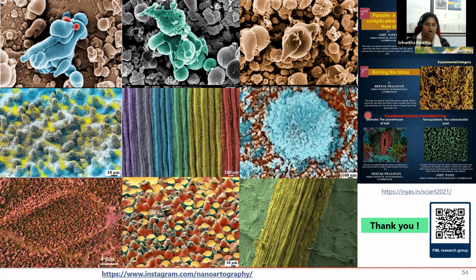So as you have seen, in all the samples, the surface roughness is reducing as we have increased the density, isn't it? Yes, madam. But remember, we are never testing a dry specimen. We are always coating or infusing the high viscosity liquid in it. And that oil is flooding your surface roughness. The oil is not having a thickness in the range of 5 nanometer. It is way higher than the roughness. So direct contact does not come into the picture.